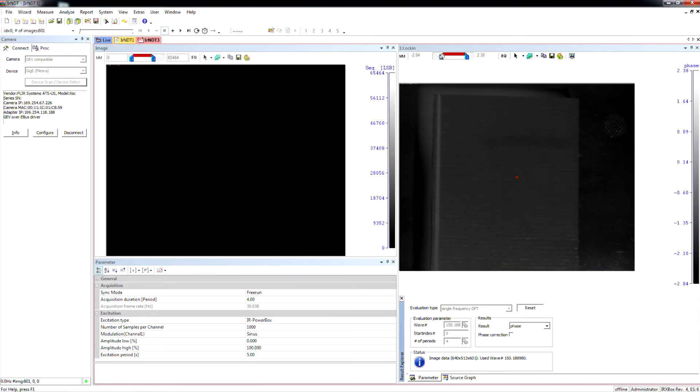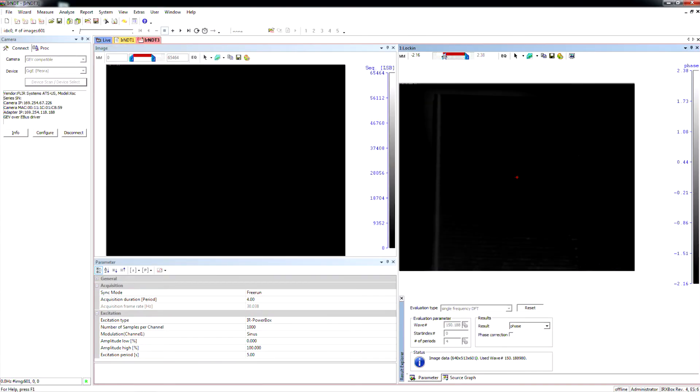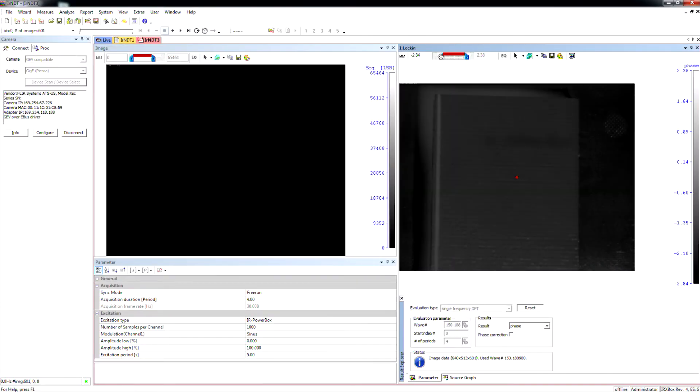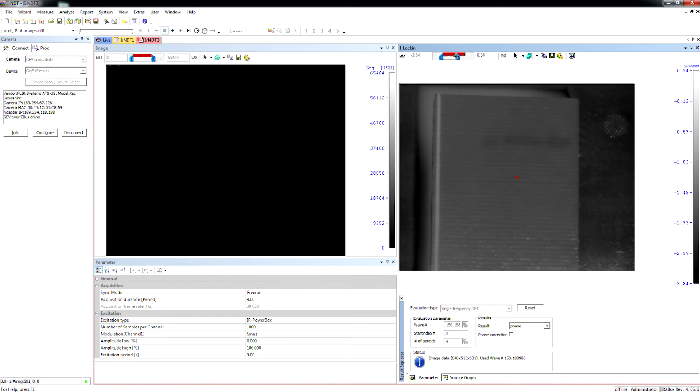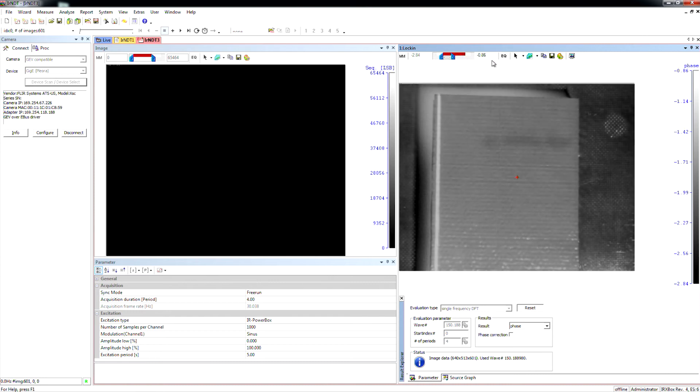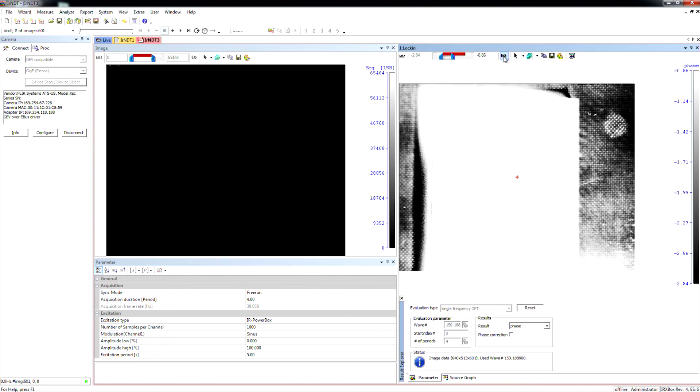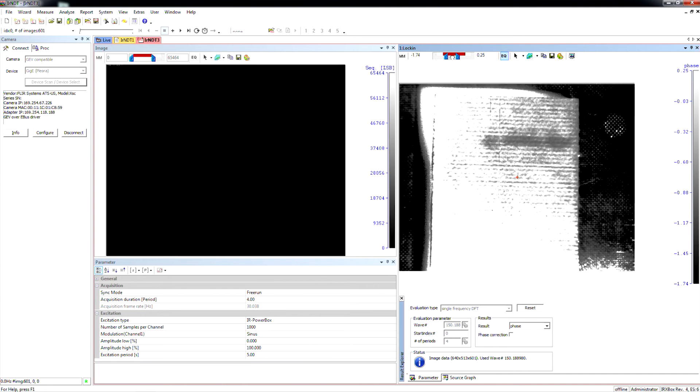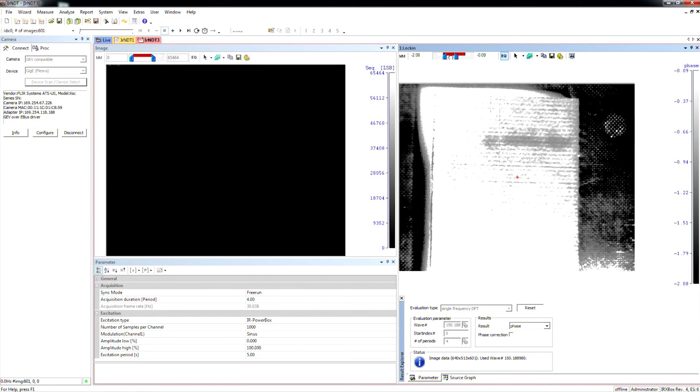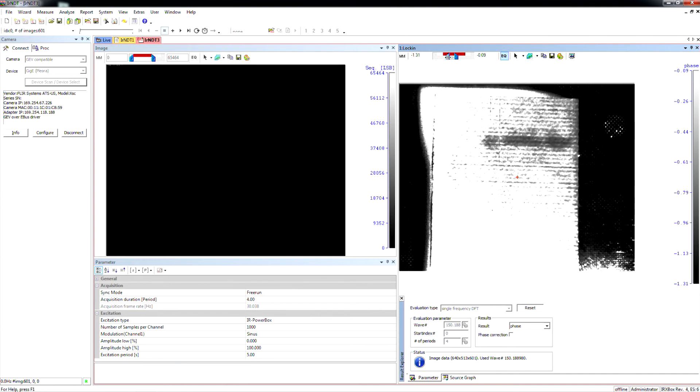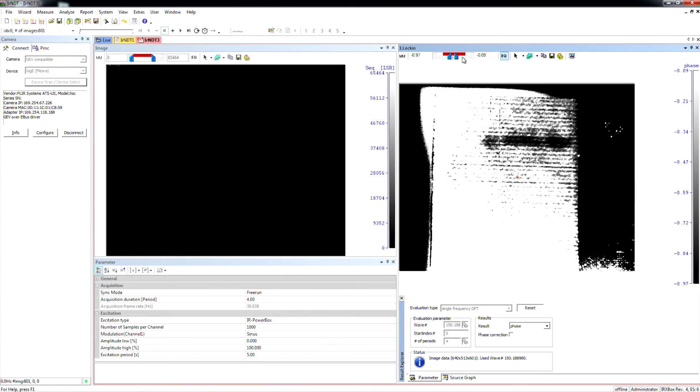So we have our first result here. I'm going to brighten it up a little bit by moving the contrast sliders. And then I'm going to turn on the EQ. And there we can see that we have a defect up in the upper right. It's fairly large. And that is most likely missing adhesive on the part. I can't see anything from the side, so I'm assuming that it's going to be missing adhesive.